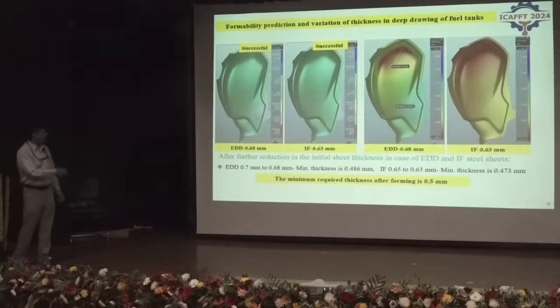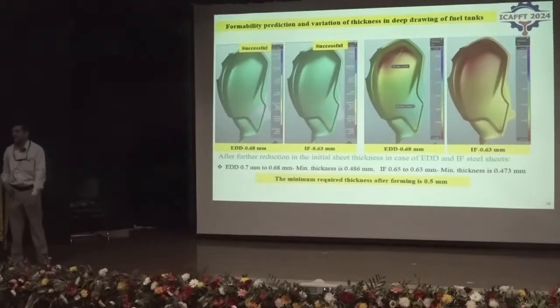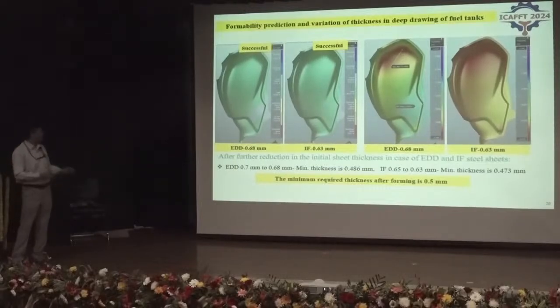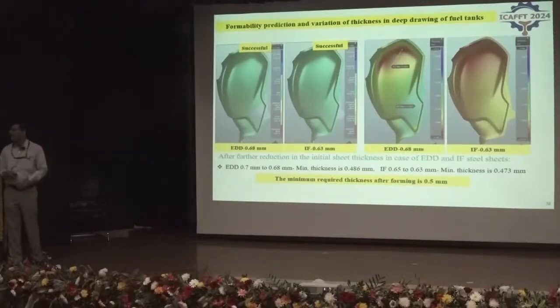So you can see that the minimum required thickness is 0.5, but the simulations have predicted that if the initial sheet thickness is 0.68, the minimum thickness would be 0.486. And in the case of IF, if the initial sheet thickness is 0.63, the minimum thickness would be 0.47. So that doesn't fulfill the requirements of the present standards. So therefore, we finally concluded that 0.7 and 0.65 are the minimum possible sheet thicknesses at which the fuel tank